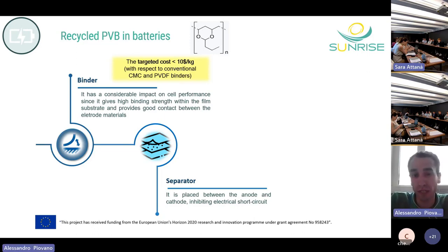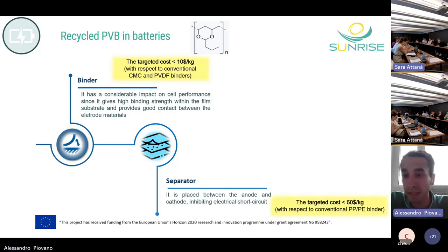We are also trying to use the recycled PVB as a separator, which is placed between the anode and the cathode and prevents electrical short circuits. In this case, the separator must be permeable to the liquid electrolyte. And here the target cost is lower than $60 per kilogram, with respect to the conventional separators that are based on polypropylene and polyethylene.